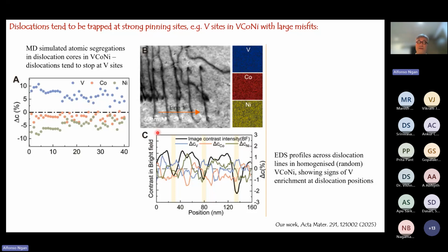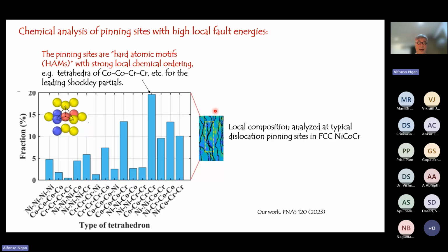So it's the segregation of vanadium in this case which would pin the dislocation, but then the segregation doesn't occur uniformly along a dislocation length on the slip plane, and therefore the dislocation would tend to be wiggling as it moves on the slip plane.